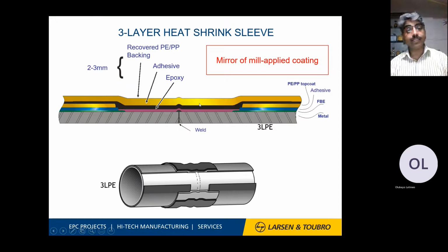Now this is very interesting. There is the 3-layer heat shrink sleeve. Normally when pipes come in two parts, they are welded at the side. This is nothing but a weld. To join this weld, we leave certain heat affected zones and some balance area for the coating to apply. Generally, as a thumb rule, it is 100 mm or 150 mm on both sides of the weld so that you can have a proper coating for already coated pipes. So you put 150 mm on one side, and whatever pipe you have is called 3-layer polyethylene, 3LPE. And the joint is coated by epoxy coating, and that is the first layer.